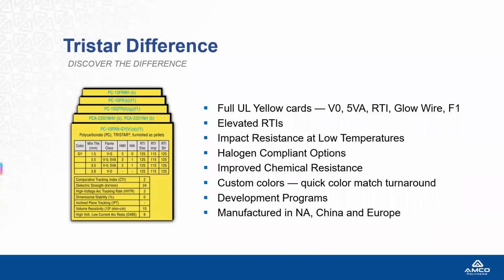So our products can maintain 50% of their property for strength, your tensile strength, after being subjected to 125 degrees Celsius for, I believe, a duration of 3,000 hours. If you looked at most polycarbonate yellow cards out there, you're going to see values between 65, 80, 85 degrees C. Just want to mention ours have the fully elevated RTIs, which is very important to the E&E, the telecommunications markets. We have options that have improved impact resistance at low temperatures, improved chemical resistance. We can manufacture TriStar not only in North America, but China and Europe as well.